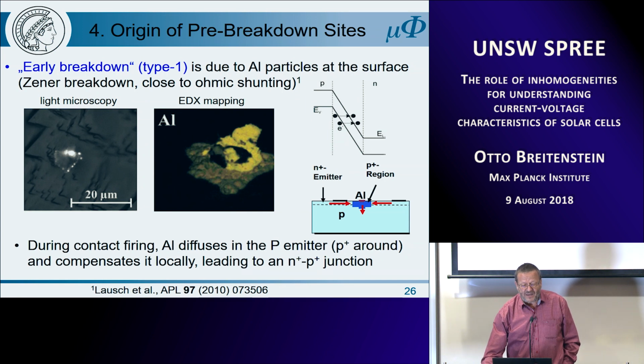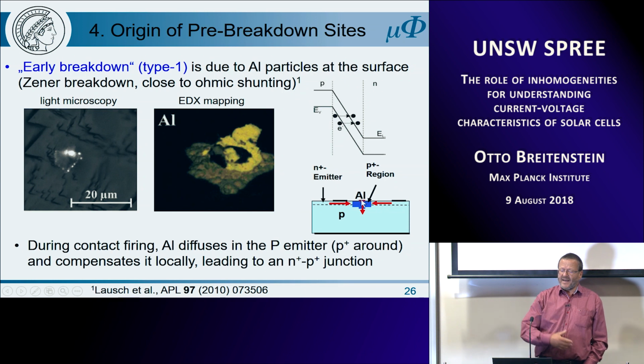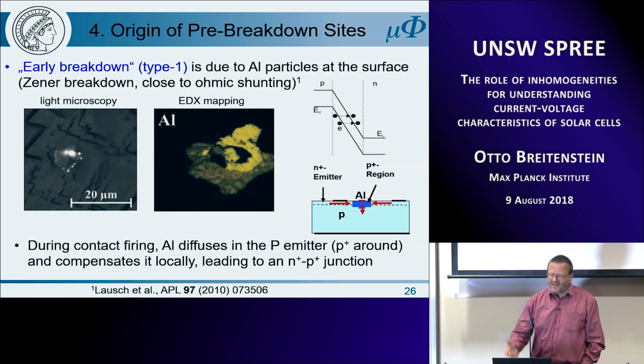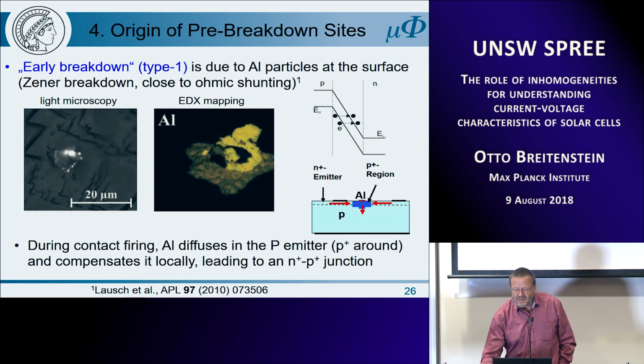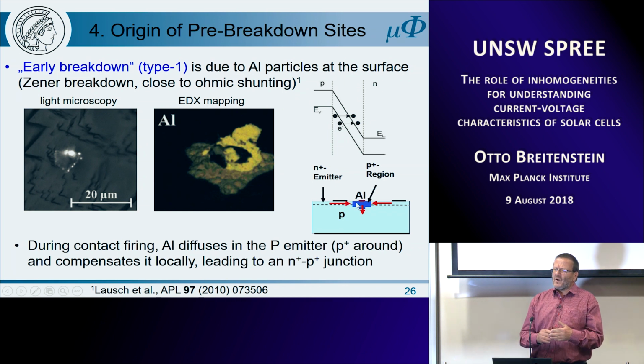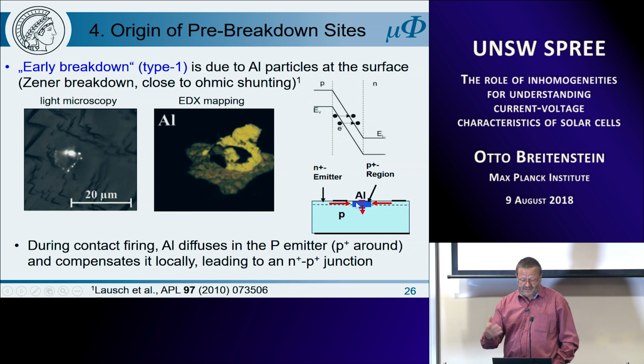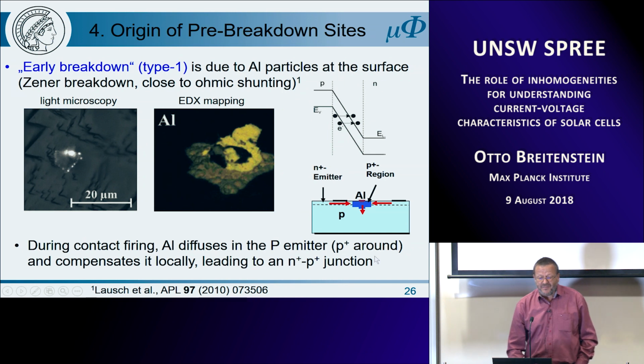So this early breakdown, which we called type 1, was identified by Dominic Lausch and co-workers. And it is due to aluminum at the surface. Here I show the mechanism. If we have a particle of aluminum at the surface, and then we have the final contact firing step, then it alloys in and leaves behind a P+ region, because it overcompensates the emitter there. The emitter is N+. And then here we have N+ P+, and that's a tunnel junction, actually a Zener diode, and it leads then to breakdown and also to visible light, as it is known for these Zener breakdowns. So that's the mechanism.